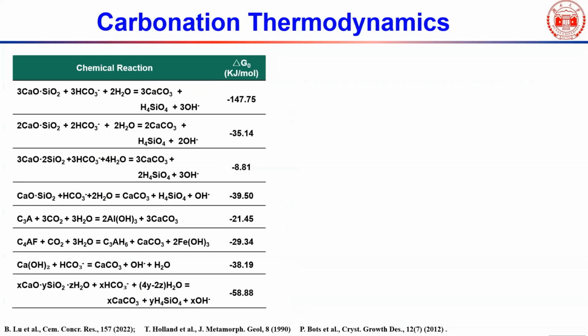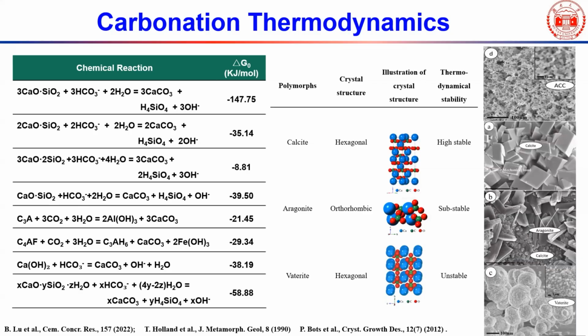And when we did some thermodynamic calculations, you can see tricalcium silicate, dicalcium silicate, monocalcium silicate, tricalcium aluminate, and all those hydrated or non-hydrated calcium silicates can be carbonated spontaneously, right? And during the carbonation, we can get four polymorphs of calcium carbonate: basically amorphous, cubic calcite, prismatic aragonite, and also spherical vaterite.